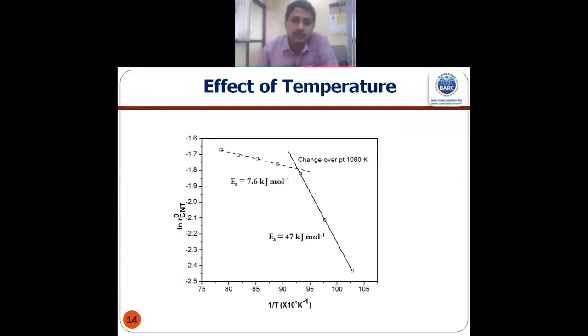So effect of temperature, as I told you, if we plot 1 by T versus ln of formation of carbon nanotube, we can see a clear-cut two regimes. One is above 807 degrees centigrade almost, and one is below. If we see below 807 degrees centigrade, the activation energy is in the order of 47 kilojoule per mole. From this value, we can have an idea that this can be chemical reaction control, because diffusion cannot have this much activation energy. And the second regime, that is above 807 degrees centigrade, is 7.6 kilojoule per mole. And here we can find that this can be a diffusion control regime.